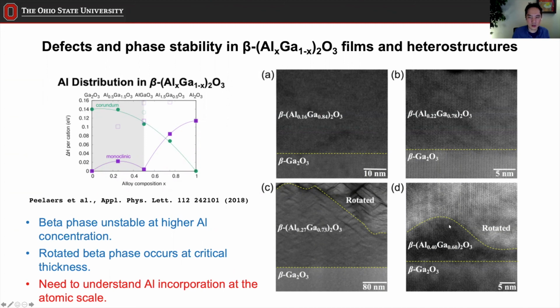Right. So is that just because of the lattice mismatch from the substrate? If so, then when you change the substrate, you may have a different critical thickness. I don't know whether there are alternative substrates to make this grow better, but another approach we're taking is to explore other growth orientations. It turns out that some orientations have a lot better growth than others, and the difference is huge because of the anisotropy of the structure. So that's being explored at the moment.